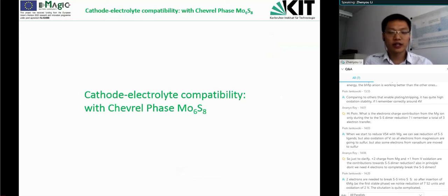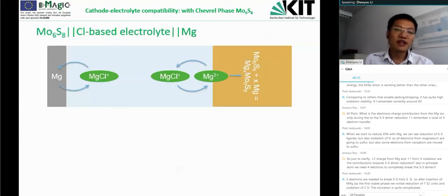So we checked the compatibility between the electrolyte and different cathodes, just to check whether it is just as we expected. The first electrode or the cathode we tried is the benchmark cathode, the Chevrel phase. And what I want to mention here is the combination between the Chevrel phase with a chlorine-based electrolyte system is not straightforward because, as reported previously, the chlorine ion has, let's say, a decisive role in the charge transfer at the interface of both the anode side and also the cathode side.